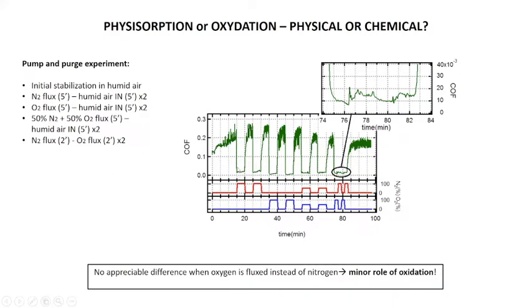If you recover the initial condition, we have again the restoring of the coefficient of friction here, and then again nitrogen. But now in the following step, we introduce pure oxygen. So at this step here and here, the chamber is saturated by pure oxygen, which is, let's say, the most favorable condition of oxidation. But anyway, you observe a very low coefficient of friction.